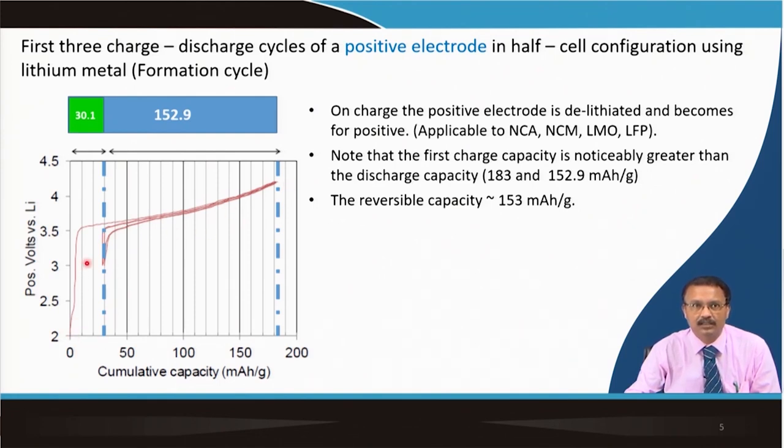Once you charge the first time, this is basically delithiated, lithium is getting extracted, and it becomes more positive because the transition metal cations are getting oxidized as lithium is going out from the system. So, plus 2 valent is oxidized to plus 3, is oxidized to plus 4, and the same thing happens for LMO or LFP. The first charge capacity that you can see is noticeably greater as compared to the discharge capacity. You are getting 183 here, and then once you do the discharge and again charge and just follow it, you will see the capacity is stabilized at around 152.9 milliampere hour per gram, which you can easily estimate from the coin cell